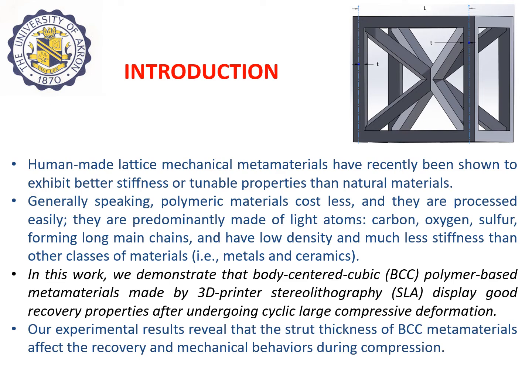In this work, we demonstrate that body-centered cubic (BCC) polymer-based metamaterials made by 3D printer stereolithography (SLA) display good recovery properties after undergoing cyclic large compressive deformation. Our experimental results reveal that the strut thickness of BCC metamaterials affects the recovery and mechanical behaviors during compression.